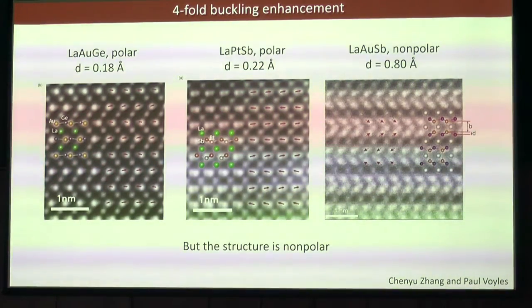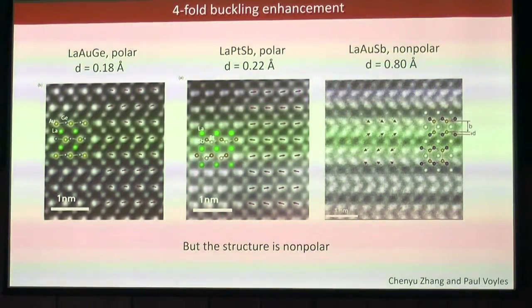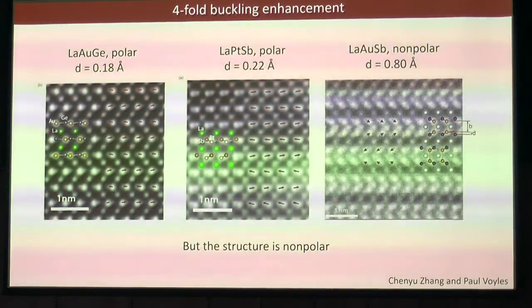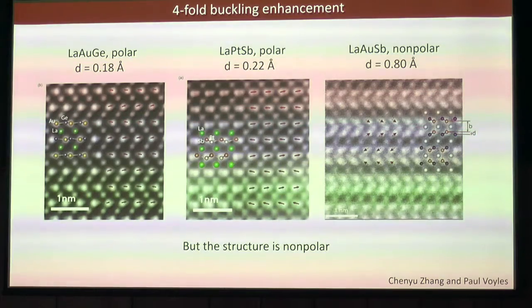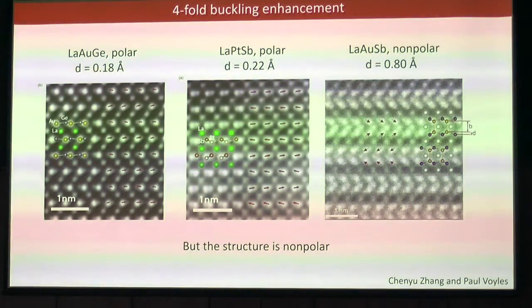I mean, this goes in the direction of the following. Some years ago, we did a study discussing the switchability of polar metals. And we showed from simulations that in a bad metal, and quite thin, you can have a non-vanishing depolarizing field, because essentially you don't have enough free charges to screen the depolarizing field. Does that make sense at densities around 10 to the 21? I think in your case you have a film that is way thicker than what we were considering, and your metal is a better metal, so it seems to me that here you should not have any depolarizing field inside. But this is something that you could try to convince your theoretical collaborators to run a simulation of. We can talk later if you want. But thank you.